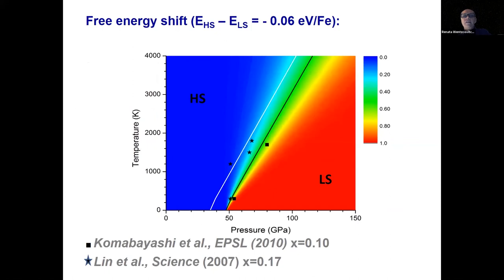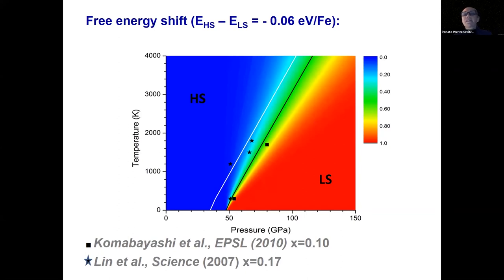This is the phase diagram today. We are still working to agree with experimental data at 300 Kelvin. DFT+U is not perfect — everybody knows that. We shifted the difference in energy between the high-spin and low-spin states by 60 meV per iron atom to be able to agree and model the velocity properties of the mantle further.